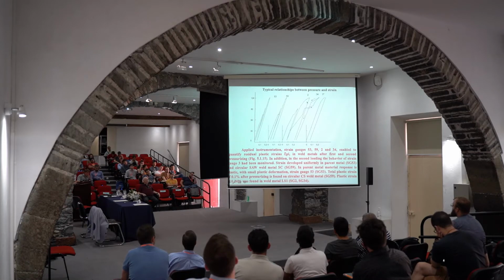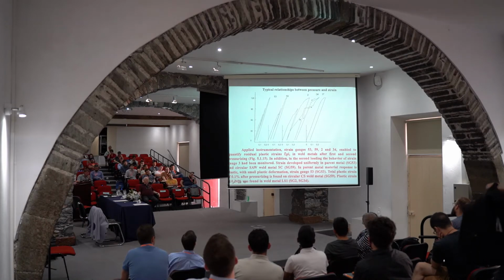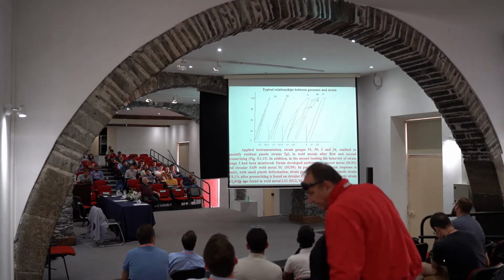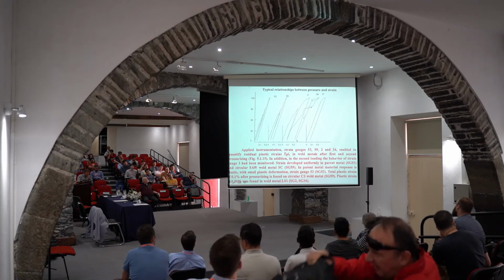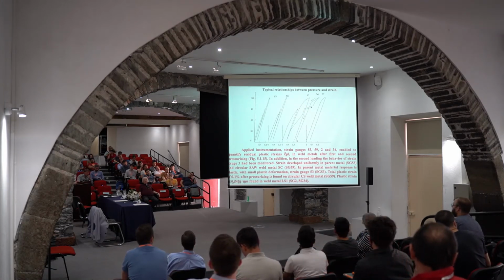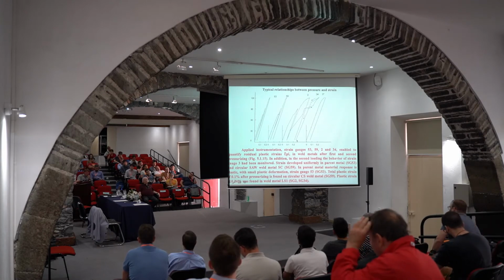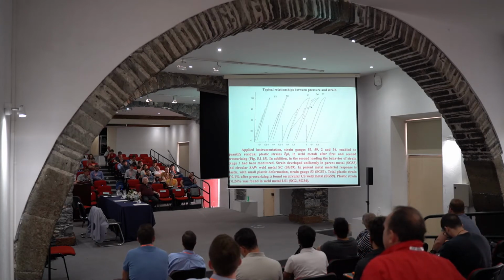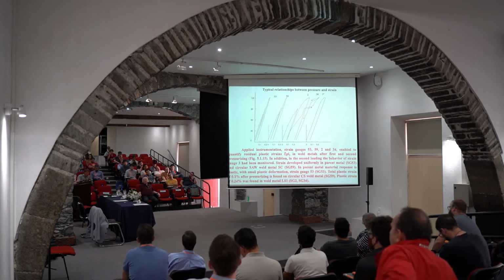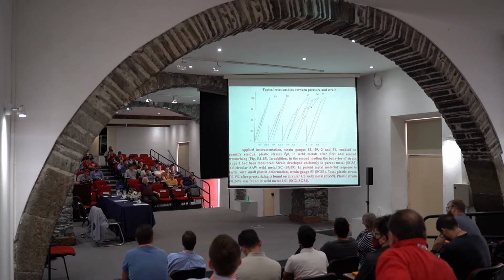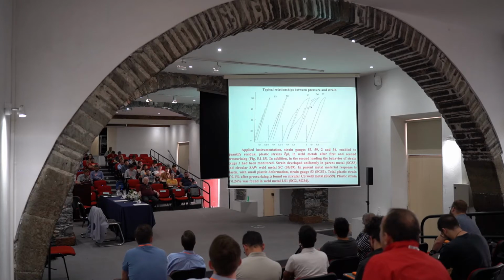Even that is not so strange as the behavior of strain gauge number 34, which goes this way first stage, then second stage, and then very strangely it goes this way. So not only is there a plastic strain here, something strange has happened in the elastic region. Probably some large elastic strains appeared because of these facts that I mentioned, stress concentration and different ratios between yield strengths of weld metal and base metal.